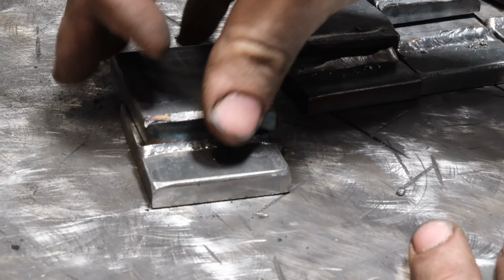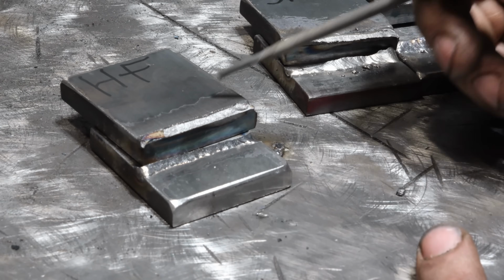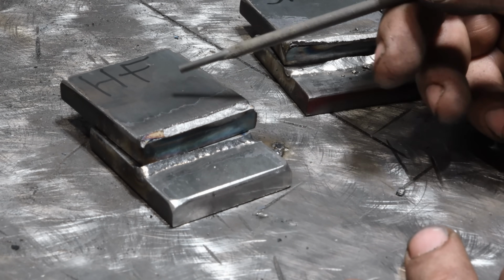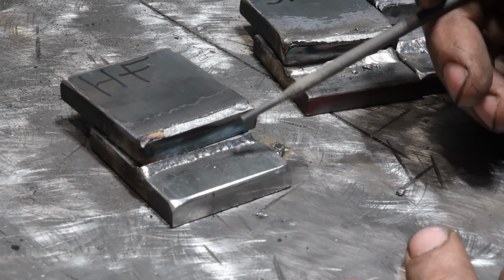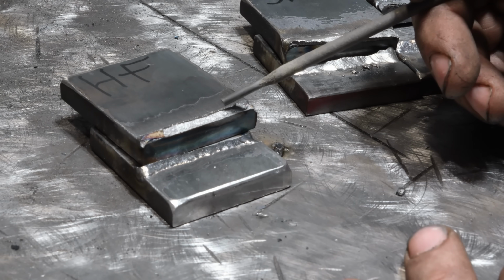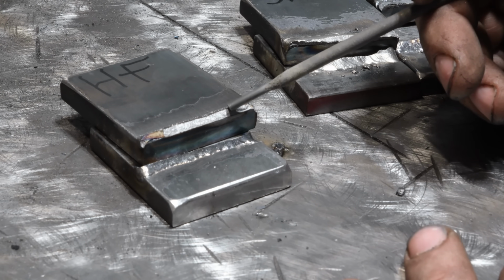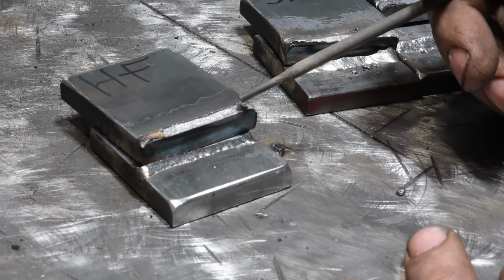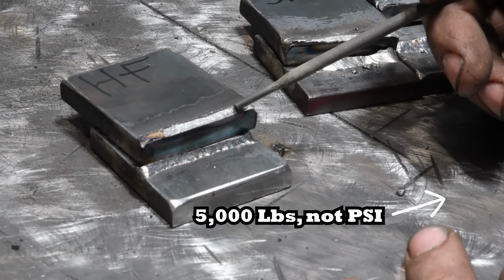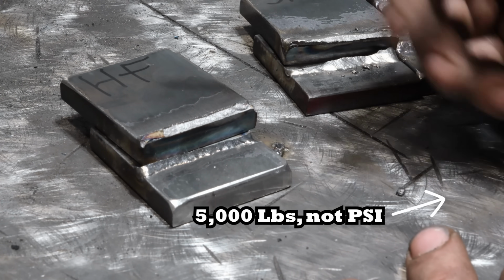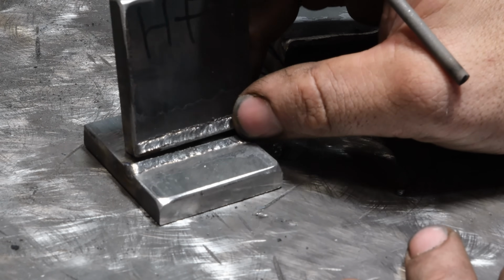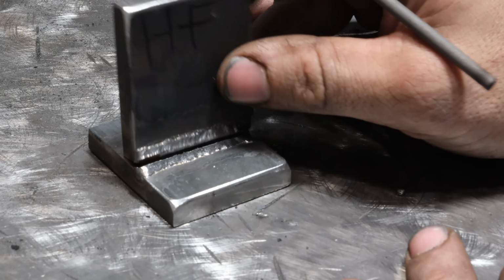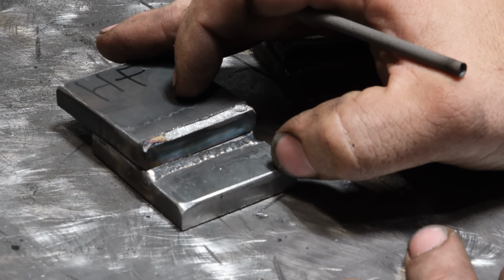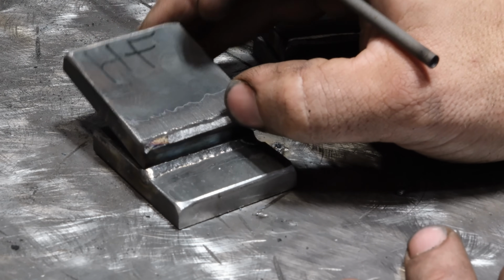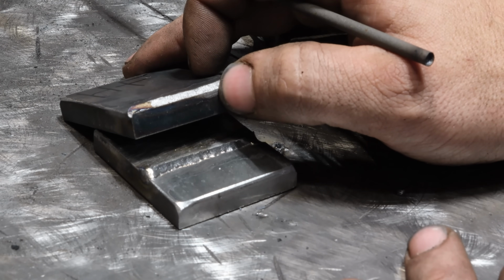Now let's look at the hard face. So the hard face is probably the most interesting bend or break result that I've ever seen testing. And it made an okay looking weld. I knew it was going to perform bad. I thought it was going to be hard as a coffin nail, and once it hit about 5,000 lbs, it was going to jet out of that press into a low Earth orbit, but that is not what happened. Literally, I put a couple hundred pounds of pressure on this and it failed. So that was hugely unexpected and pretty wild if you ask me.